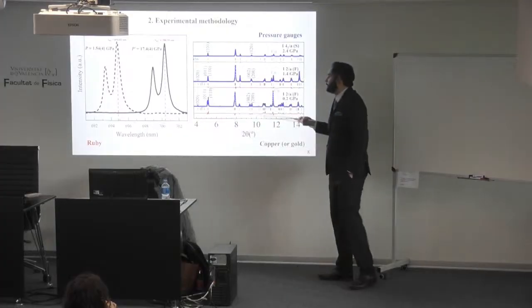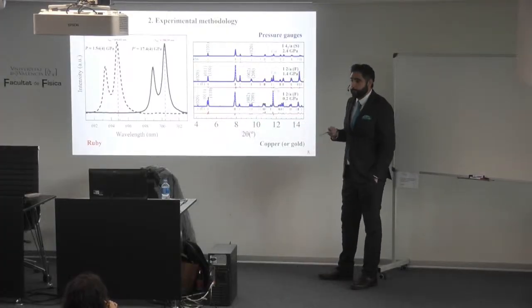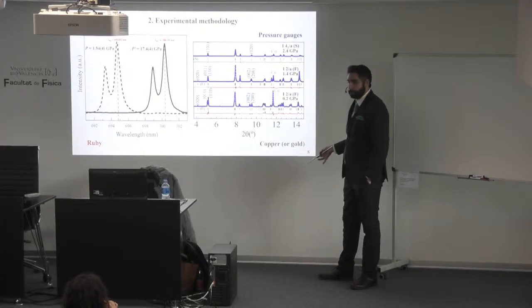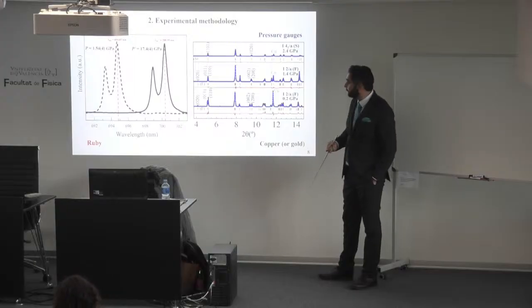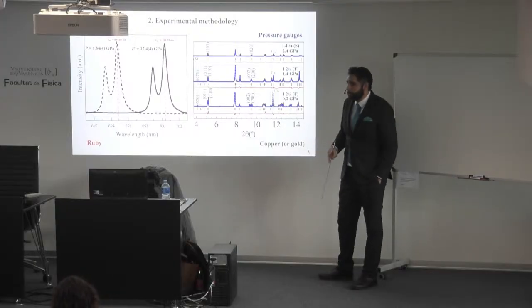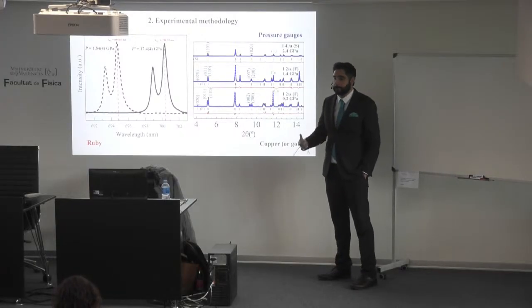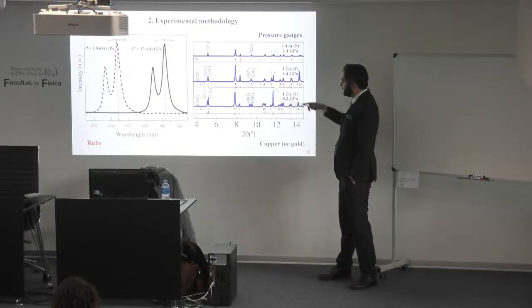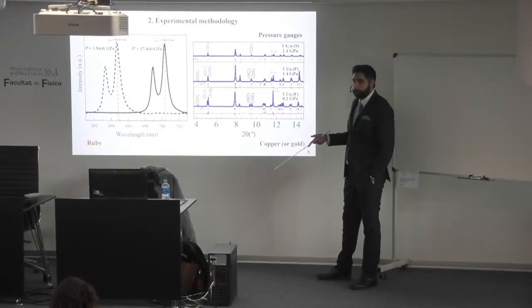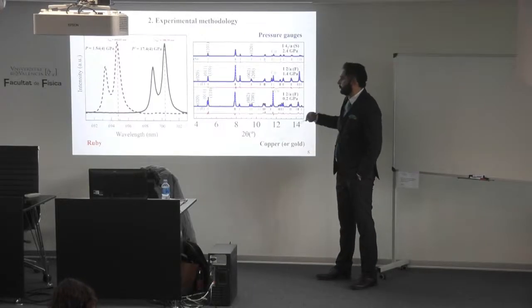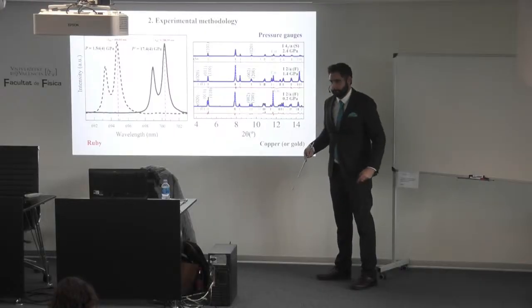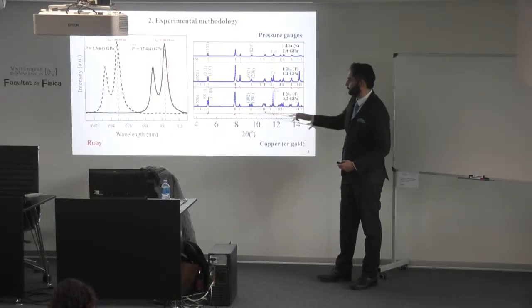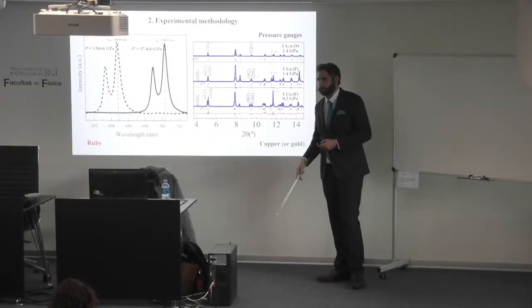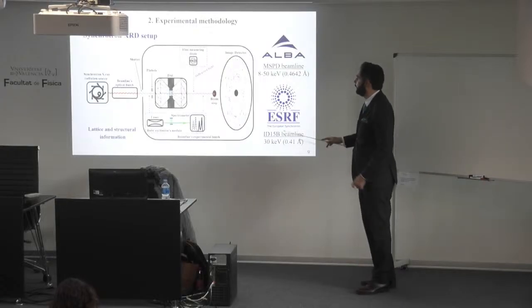But sometimes in XRD experiments, if we are able to put some copper or gold inside the loading, as it is cubic, it is not going to react with the sample, and it's easy to find because it has fewer peaks. It can accelerate the process. But I think ruby is more trustworthy for this case.